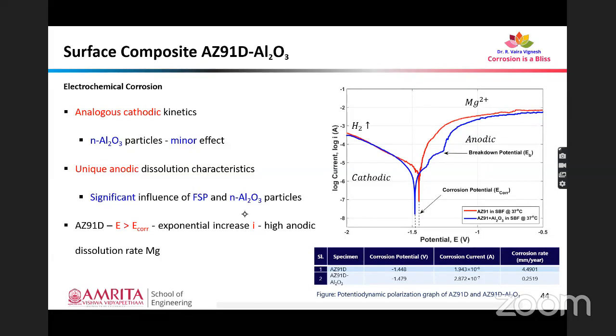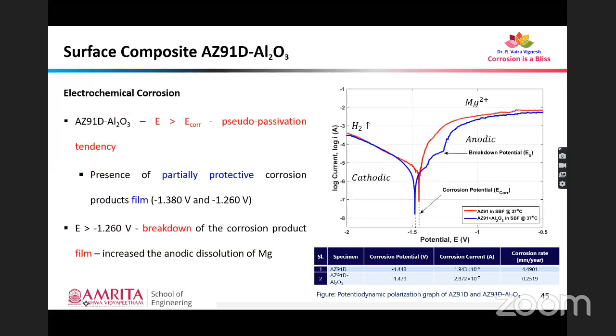And even before that, let me clarify the cathodic and anodic kinetics. The electrochemical corrosion analysis has given us an idea that there is analogous cathodic kinetics. That is, there is minor influence of nanophase alumina particles over the corrosion phenomenon of the material. However, there is unique anodic dissolution characteristics. So we can obviously see, if the potential is increased beyond the corrosion potential, there is an exponential increase in current in case of AZ91D, that is the base material. So that resulted in high dissolution rate of magnesium from the material. But in the case of the composite, we can see a pseudo passivation tendency.